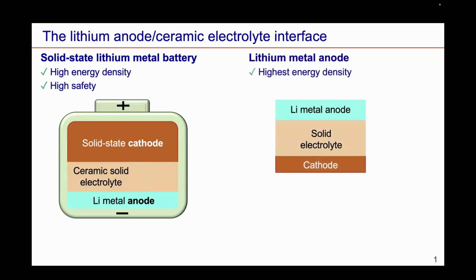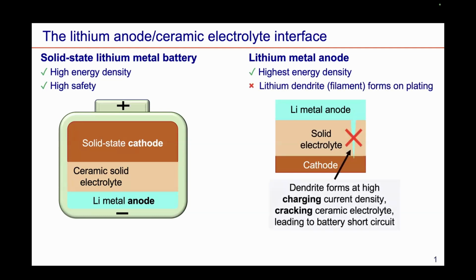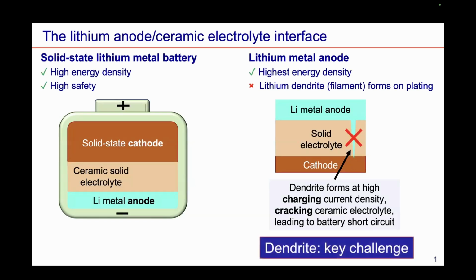The lithium metal anode exhibits the highest energy density among all the anode materials. However, it is extremely difficult to achieve fast charging for these anode materials. This is because lithium filaments grow within the electrolyte, which will crack the electrolyte and lead to battery short circuits under a high current density. These lithium filaments are normally referred to as lithium dendrites, and dendrite growth is one of the biggest obstacles for the application of solid-state batteries.